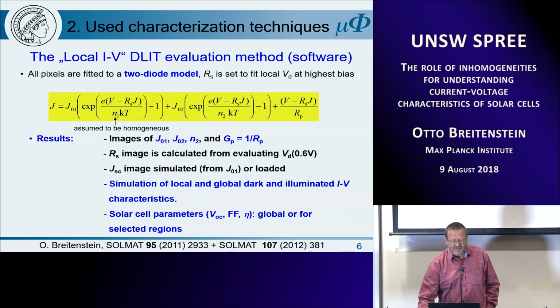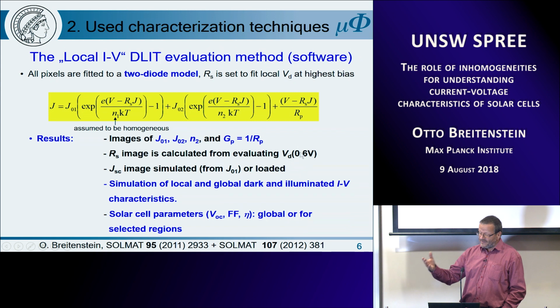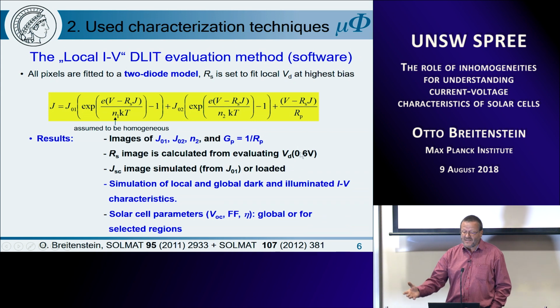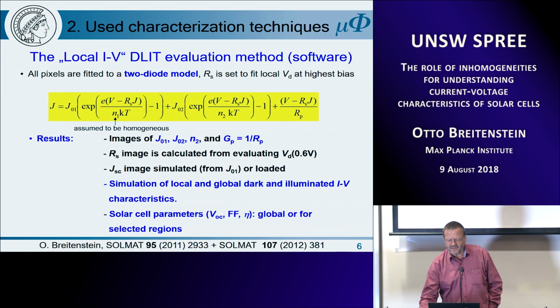So the results are images of J01, J02, N2, which is also used as a local parameter, and the ohmic conductance, which is the inverse of the parallel resistance. So we need a series resistance image, which is usually calculated from evaluating the local diode voltages, which we can obtain by luminescence imaging. I will explain this in detail in the next talks.